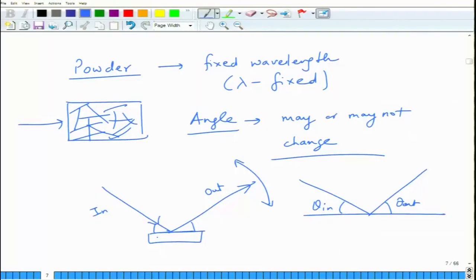So, in case of a powder specimen, since there are multiple orientations present all over the place, you will have diffraction taking place. All you need to do is keep the X-ray beam fixed, you can keep even your sample fixed, you can just move the detector. Whereas, in case of single crystals, you may have to move the sample, you may have to move the incoming beam as well to get the maximum diffraction possibility.